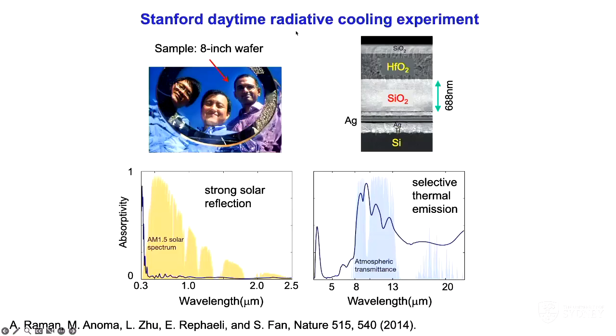What we're staring at is a mirror made on an 8-inch wafer. This mirror is made by depositing a thin film of silver on top of silicon, which becomes the primary reflecting layer. Then on top of silver, we put multilayers of hafnium oxide and silicon dioxide. In this system, the thermal radiation primarily comes from silicon dioxide. The silicon atom and the oxygen atom at room temperature oscillate against each other, and that emits thermal radiation. The hafnium oxide was put in to further shape the thermal emission spectrum.